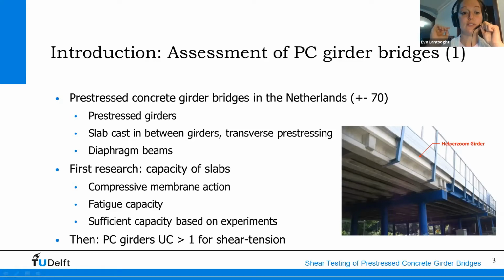Now, previous research has shown that in these cases, compressive membrane action causes the capacity to be much larger than what we would find from the code equations, and that this mechanism does not break down under fatigue testing. So we actually could conclude after a lot of testing that the slabs are not the governing members. What is governing for assessment now are the pre-stressed concrete girders, which have a unity check larger than 1 for shear tension, for the failure mode of shear tension.